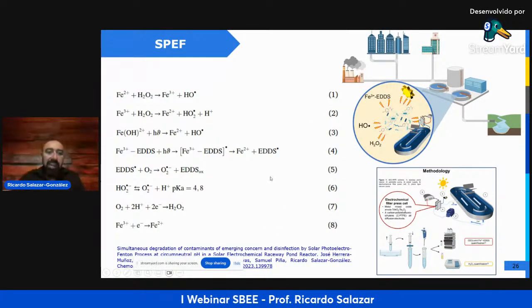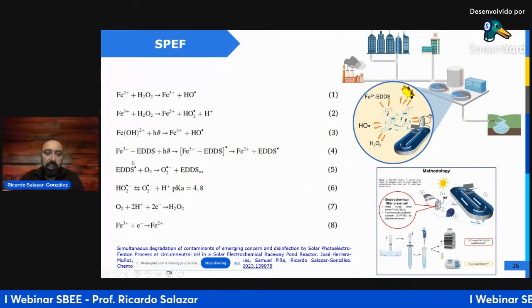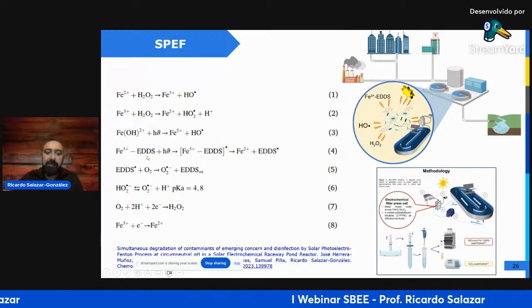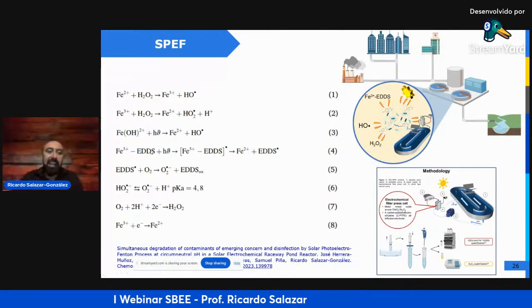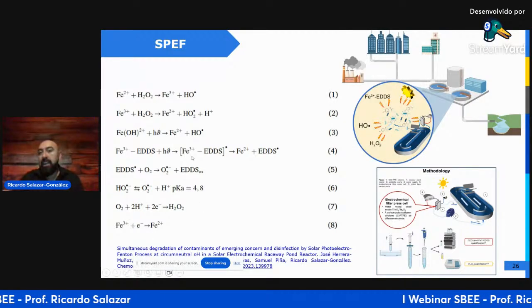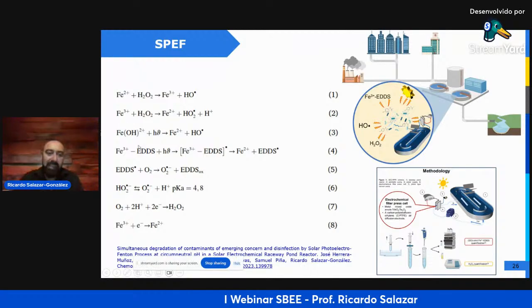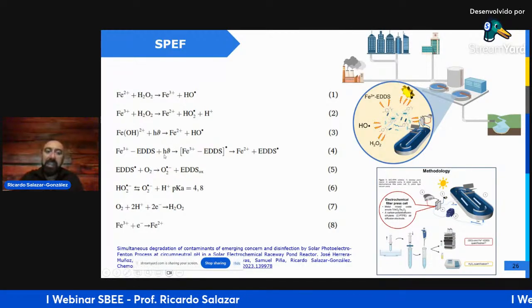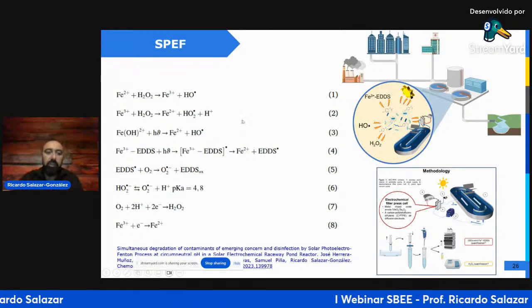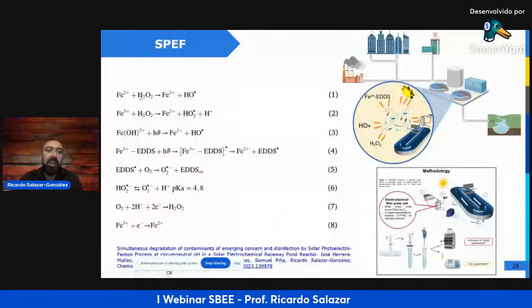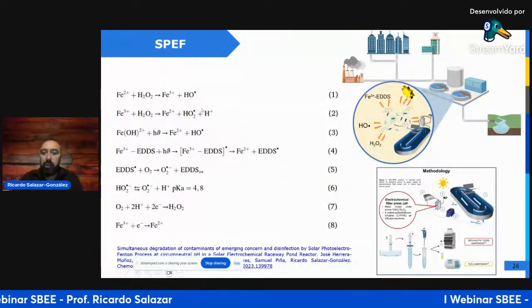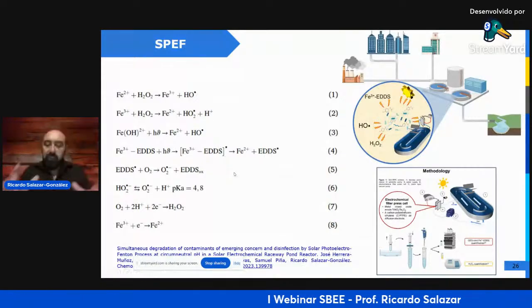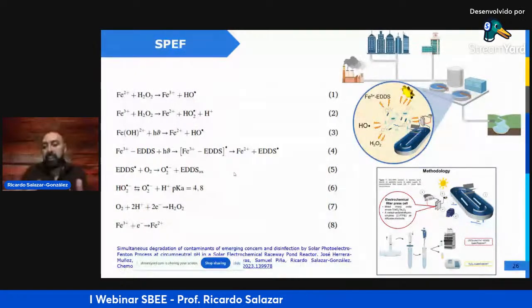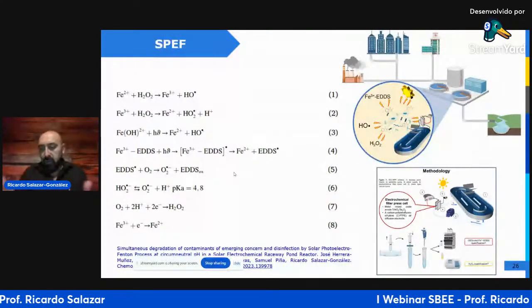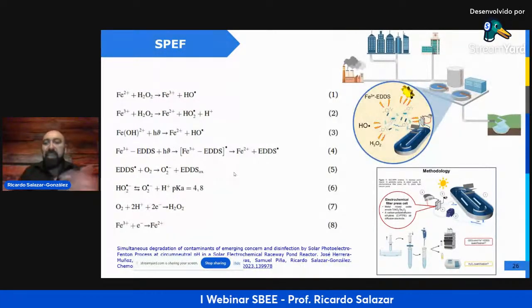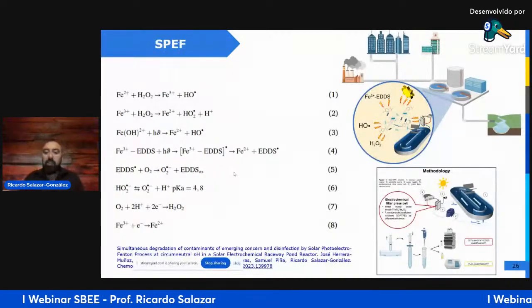So in this work, we treat the real wastewater using a complex between iron 3 and EDDS. EDDS produces a complex with iron 3, maintaining iron in solution, and this complex is photolyzed with the UV radiation from the sun, producing iron 2. Iron 2 goes to the Fenton reaction, reacts with the peroxide, producing hydroxyl radicals. So we can treat this real wastewater in our solar electrochemical reactor without change in the pH of the real solution.